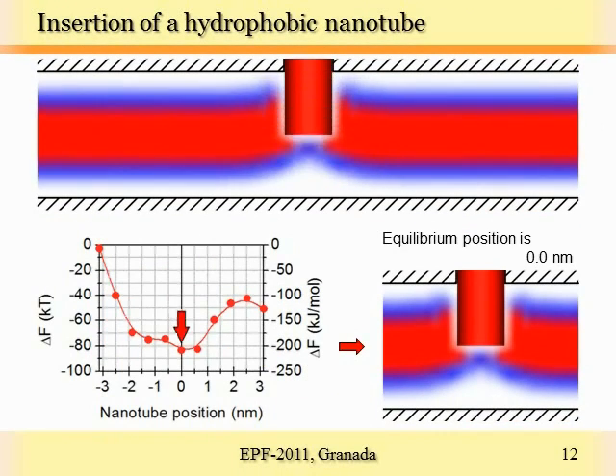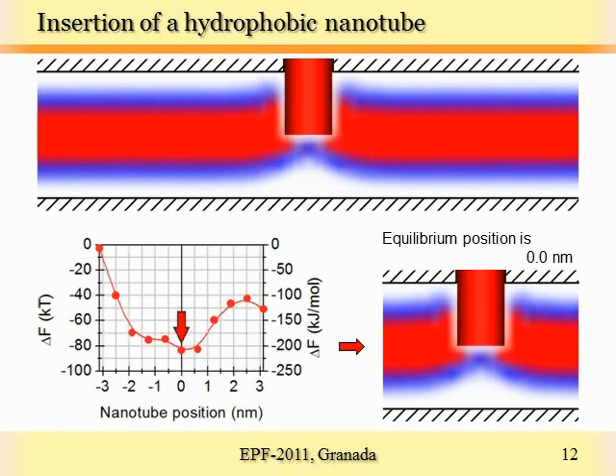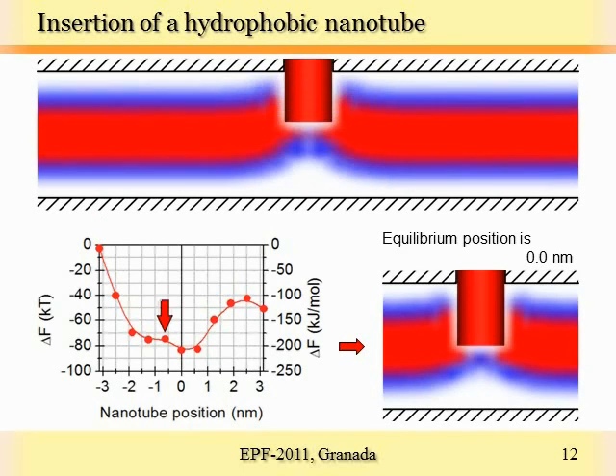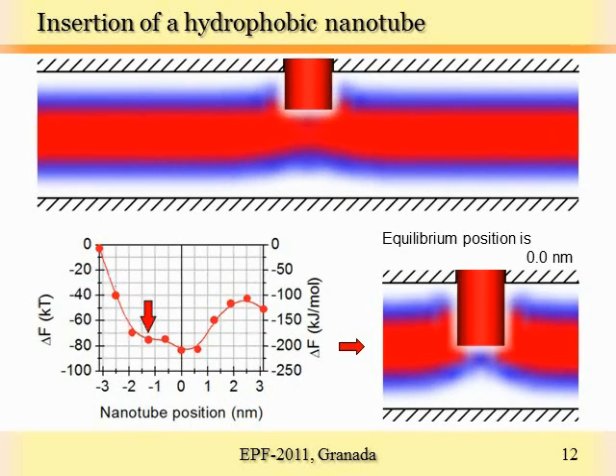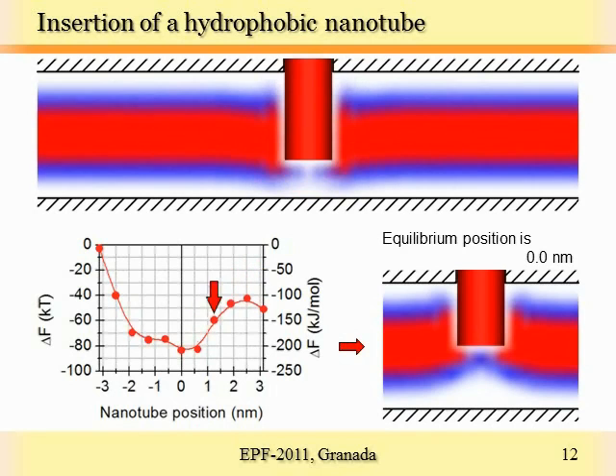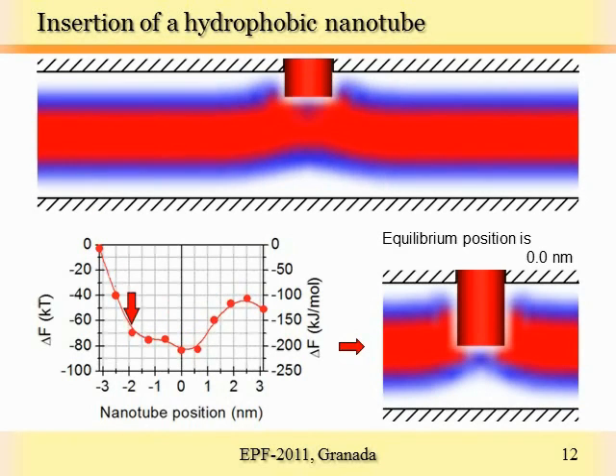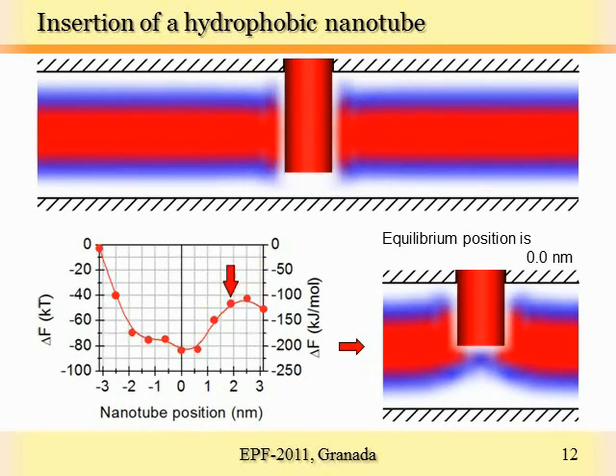In the case of a hydrophobic nanotube, the situation is opposite. You can see that the hydrophobic core of the membrane actually likes to be in contact with the surface of the nanotube, and when we insert the nanotube inside the membrane the energy goes down. But then it gets stuck, because in order to translocate through the membrane you must pull the nanotube out from the other side, and you must cross an energy barrier from the minimum to the maximum, which is too high. And actually, if you give the nanotube freedom to change its orientation, it will prefer to flip and lie parallel to the bilayer.